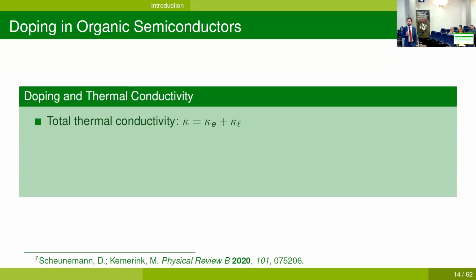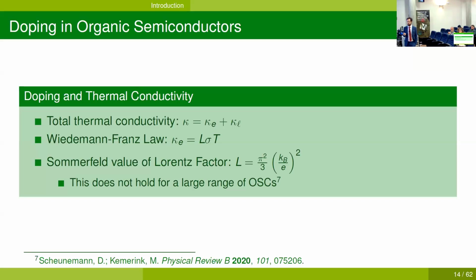Moving to the effect of doping on thermal conductivity, we know that the total thermal conductivity of any material can be expressed as the sum of an electronic component kappa E and a lattice component kappa L. Kappa E, the electronic component, is related to the electrical conductivity through the Wiedemann-Franz law, where this factor L is called the Lorenz factor. The Lorenz factor is usually assumed to take on the Sommerfeld value, which is the maximum theoretical value, and which has this expression.